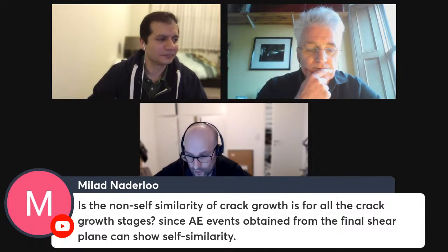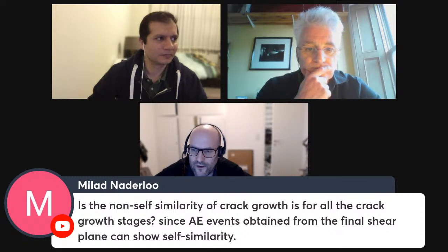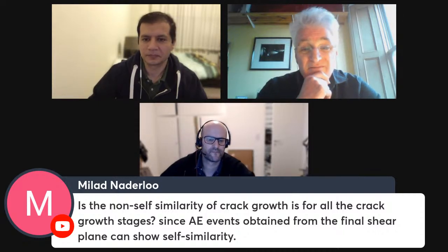So there are a few more questions by Milad Nadalo, asking if the non-self-similarity of crack growth holds for all the crack growth stages, since acoustic emission events obtained from the final shear plane can show self-similarity. I mean, the self-similarity of acoustic emissions, with constant stress drop, has been shown across about 15 orders of magnitude. It's really phenomenal. It's almost as broad a bandwidth as the fractal objects you get in a cloud. So the source mechanics of the acoustic emissions are very scale invariant.